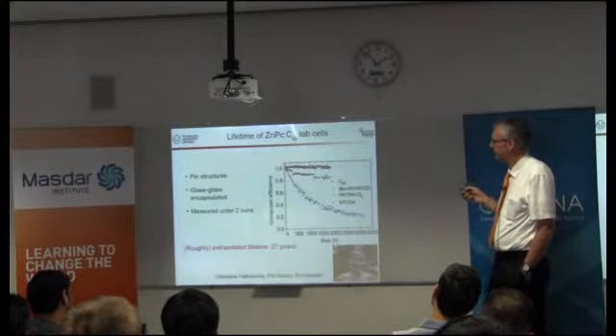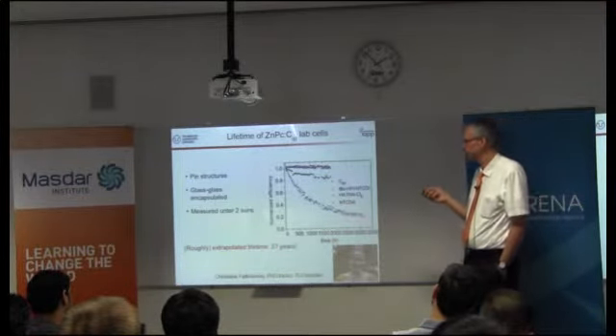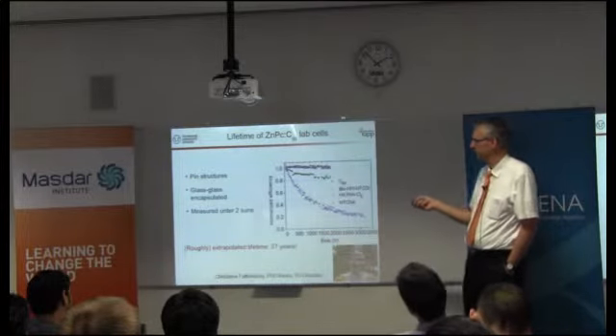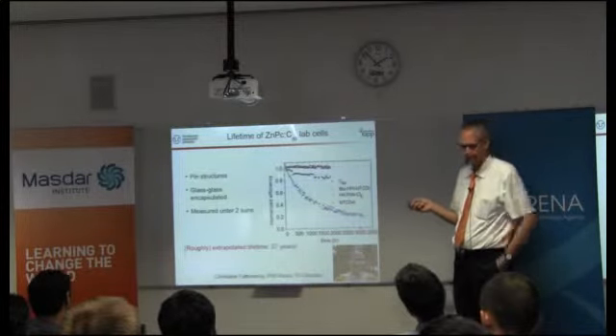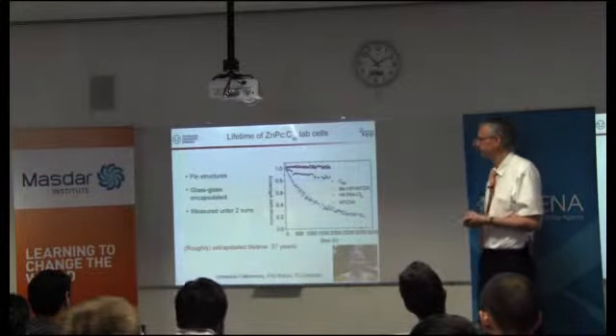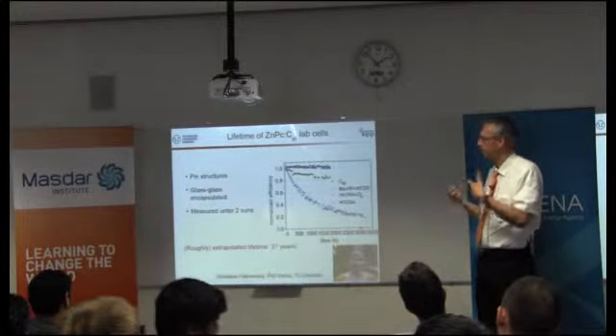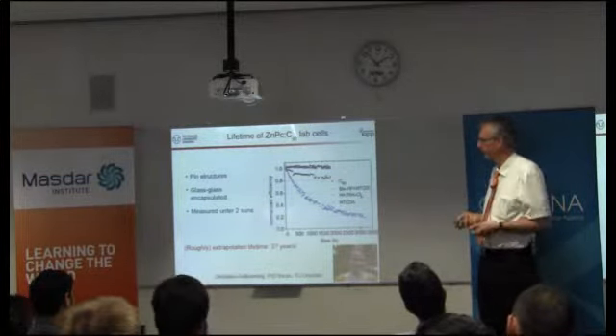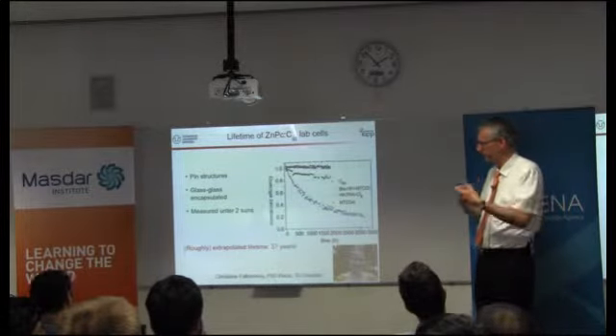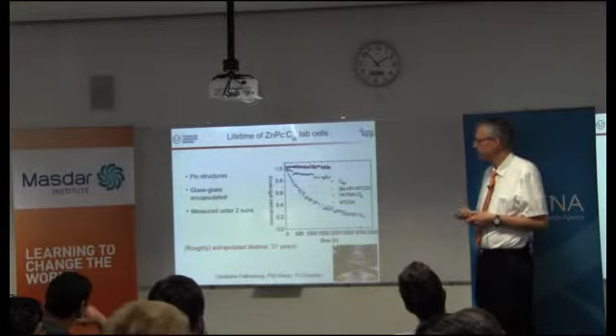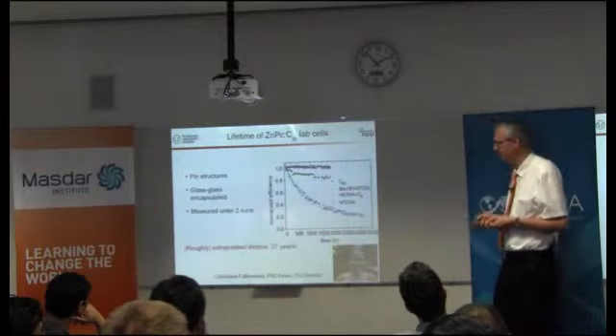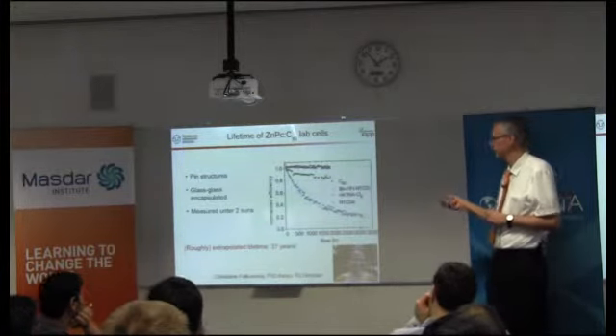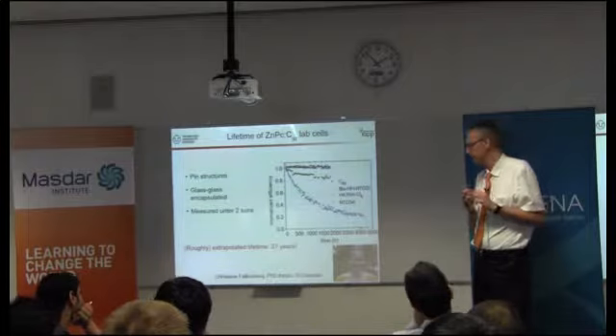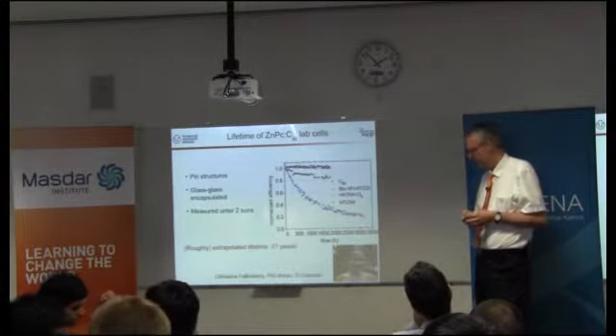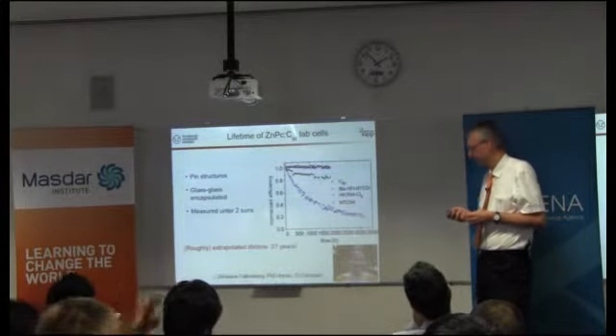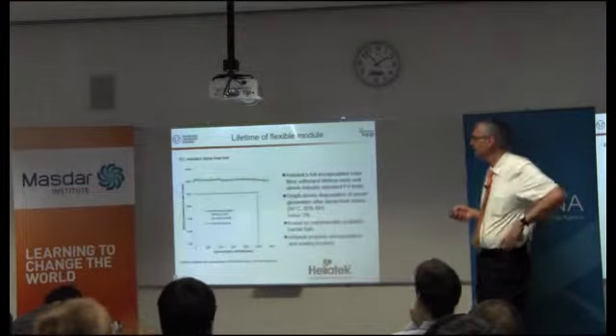Although there is one point which has to be treated with care, and that is this is between glass sheets. In practice we use plastic substrates, where the water and oxygen which degrade can diffuse through, while glass is absolutely tight. So this is only to demonstrate how stable these materials are. Another point which is not mentioned here in the slide is you need to block UV. If you do not block UV, organics cannot survive that, but that can be done.